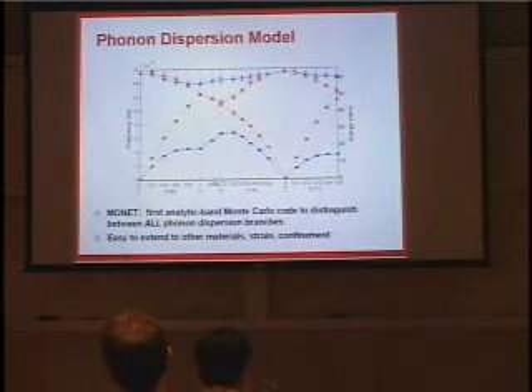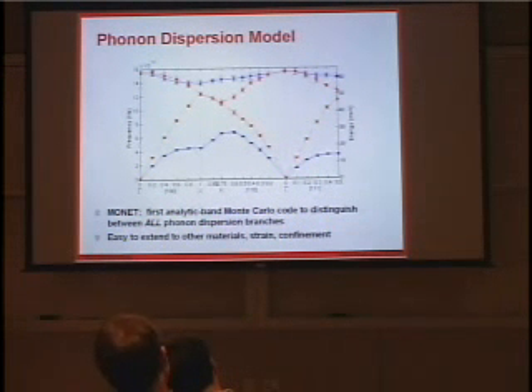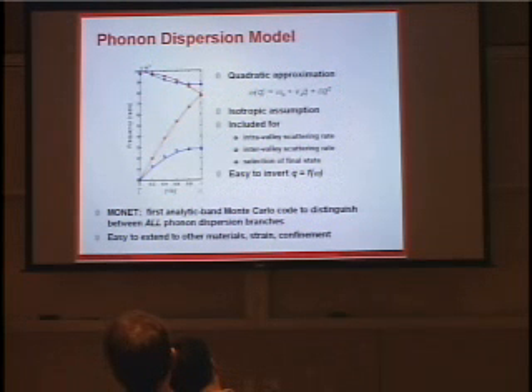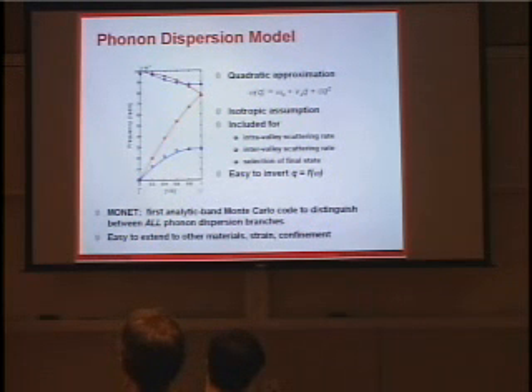Again, I'm starting with the full phonon dispersion from neutron scattering data plotted in silicon along the 3 main crystal directions. What I've got here, again, is the frequency on the right. It's the equivalent energy in milli-electron volts for these phonons, and on the horizontal axis, the wave vector. And what I've done is I've looked at this, and I've said, I can use just the 100 part of this dispersion relationship and assume it to be isotropic all the way around. So that's what I've done, I've looked at just the 100 direction of the phonon dispersion in silicon.